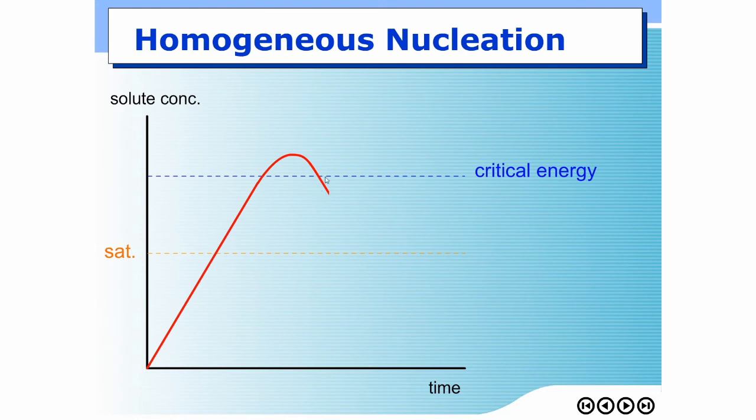But you should see that at this point, the concentration of growth species in the liquid still exceeds saturation. Okay? But it is less than critical now. So no more nucleation will be formed because it is lower than the critical point. But the concentration still exceeds the saturation. Still, the solution is not stable. The solution needs to kick solute out. But nucleation cannot be formed.